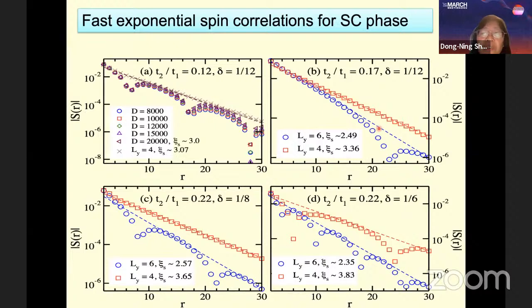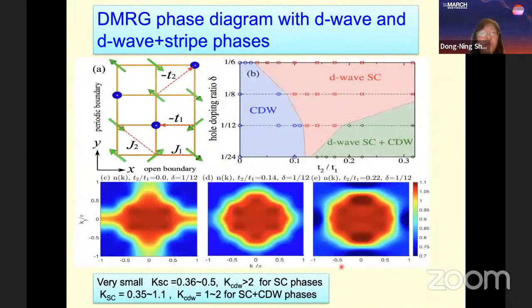In those different phases, the spin correlation always decays exponentially. However, the exponent of spin correlation varies for different parameter points, and it decreases slightly when we go to the 6-leg ladder.